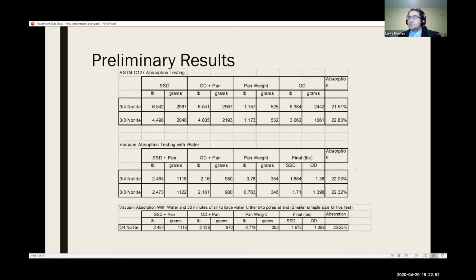have similar absorption percentages. And then finally, we ran an extra test, a method where after we have finished with the vacuum method, we let air into the chamber for 30 minutes to push water further into the aggregate. However, this resulted in only a 1% increase in absorption, so it was not very different.